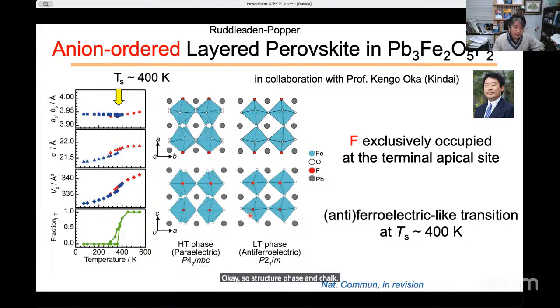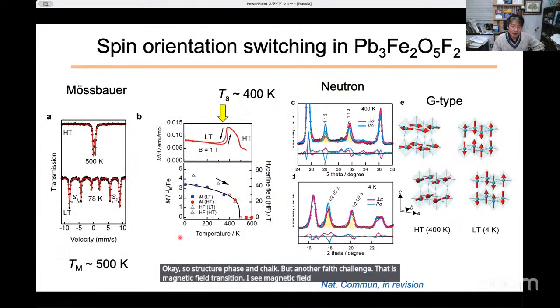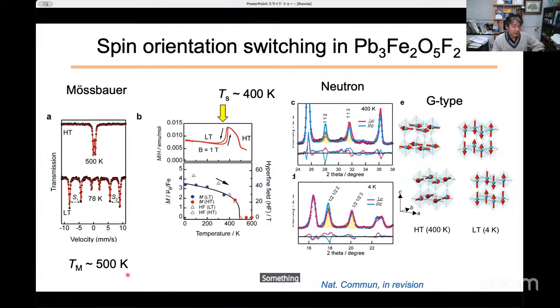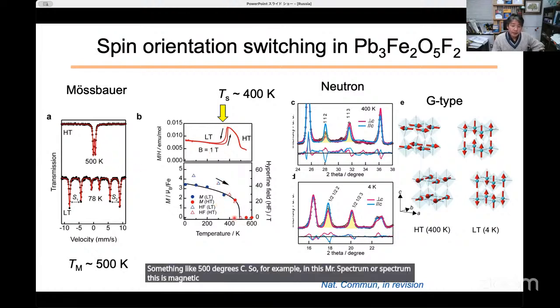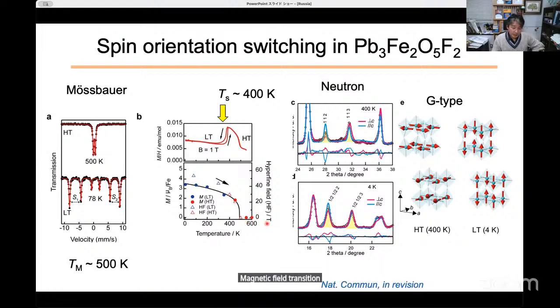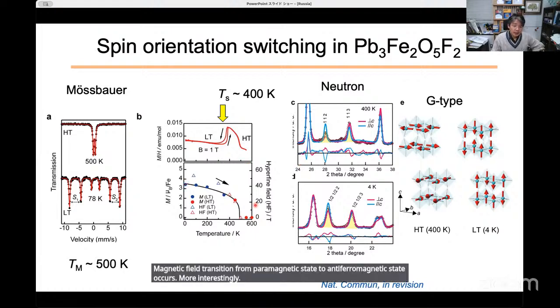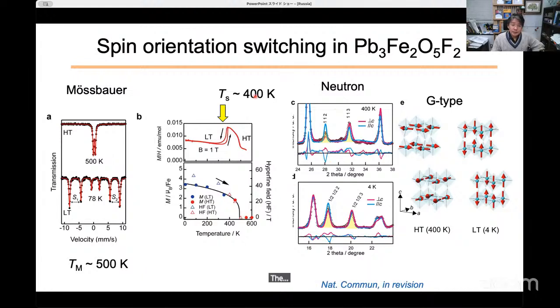Okay. But there is another phase transition, that is magnetic phase transition. Actually, the magnetic phase transition occurs at a higher temperature, something like 500 K. So, for example, in this Mössbauer spectrum, or this magnetic susceptibility, you see that at 500 K, the magnetic phase transition from paramagnetic state to anti-ferromagnetic state occurs. More interestingly, the spin orientation switching occurs at the structure phase transition.